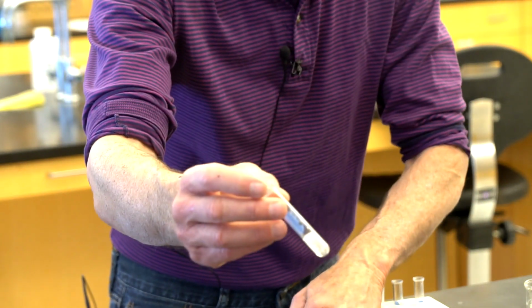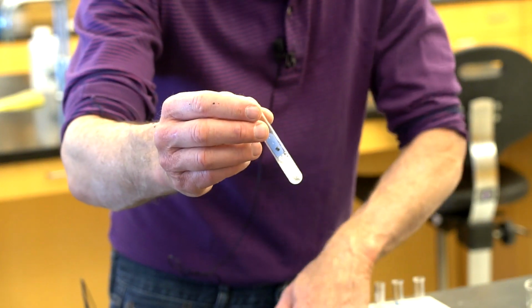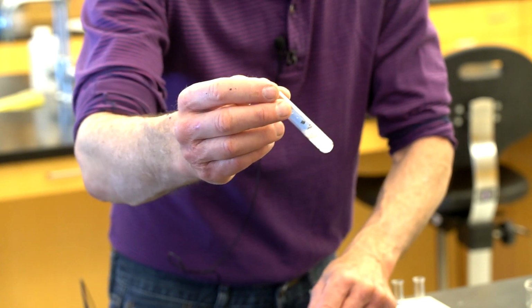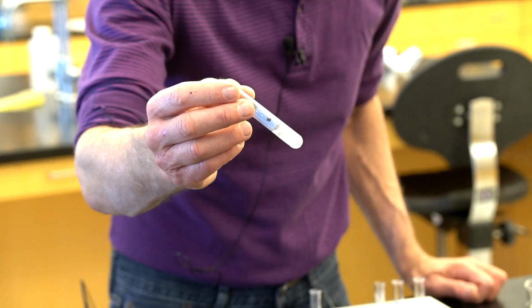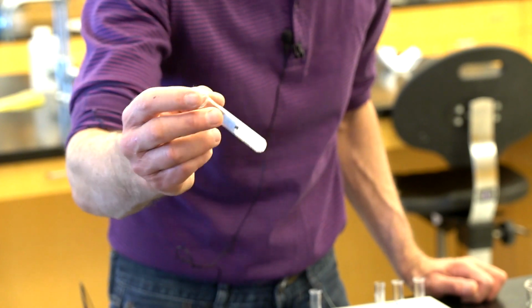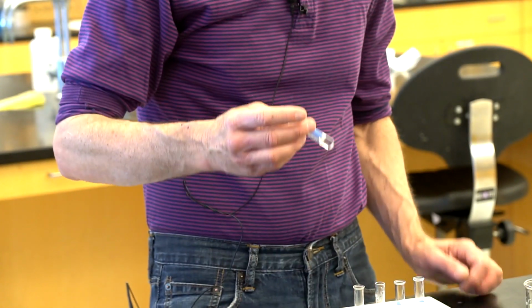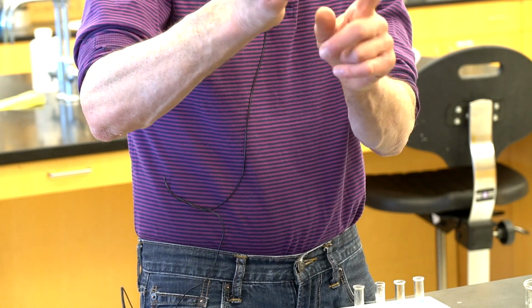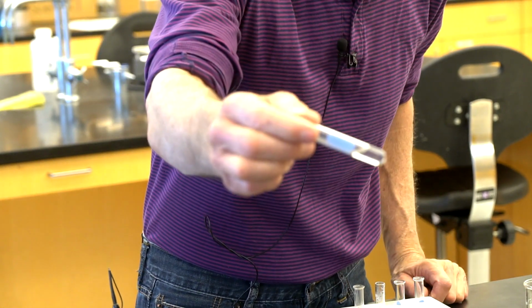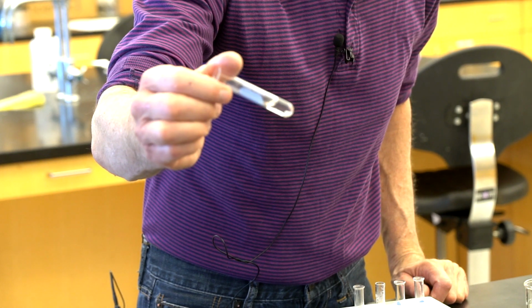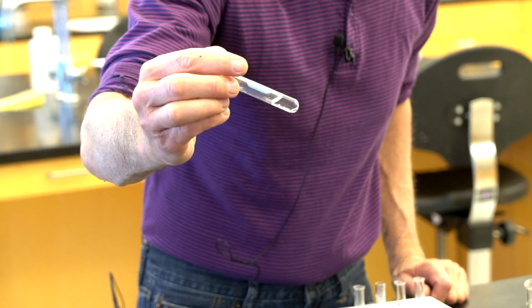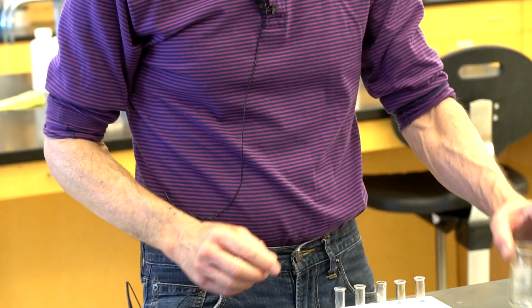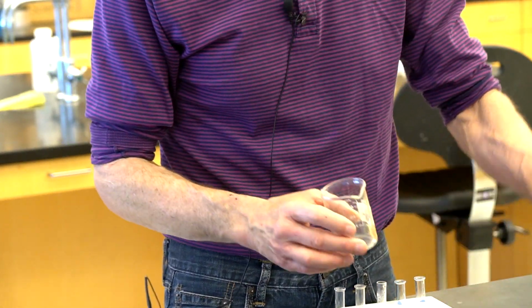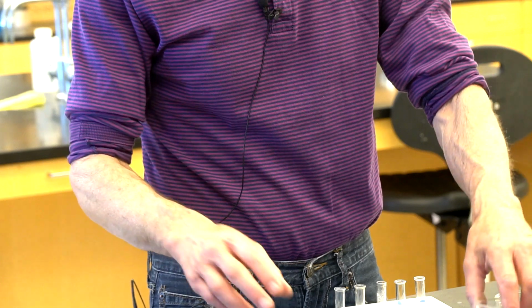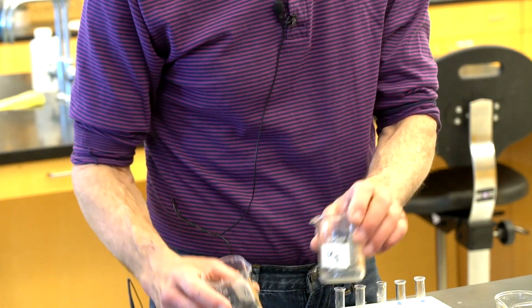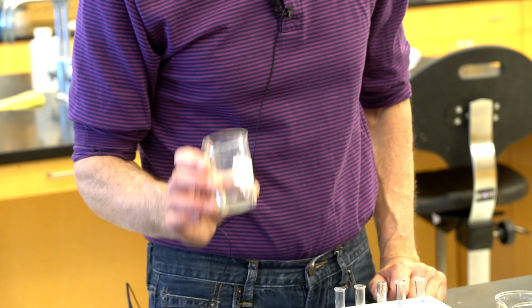Putting magnesium in the hydrochloric acid, you can see quite a vigorous reaction. Vigorous bubbling, producing hydrogen gas at a high rate. Very exciting. Meanwhile, our aluminum is sitting at the bottom of the test tube, not doing too much. So for that observation, I guess you'd put down very little reaction. So for zinc, moderate reaction, copper, no reaction, tin, very little reaction, magnesium, vigorous reaction, and aluminum, very slight reaction.